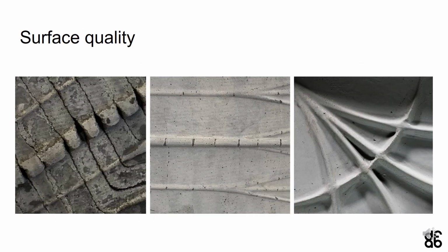The resulting surface quality of the soffit is a function of the viscosity of the concrete mix and the trajectory of the print path. As earlier mentioned, for the first prototype, the tool path was independent from the geometry. In the second prototype, shown in the middle image, the tool path followed only the major ribs, leaving the smaller ribs with imperfections. For the final demonstrator, the initial layer of the tool path followed the entire geometry of the soffit, resulting in the best surface quality.